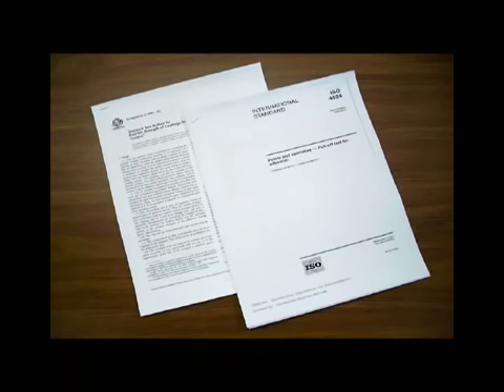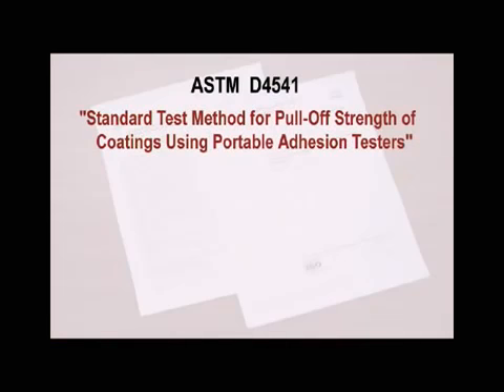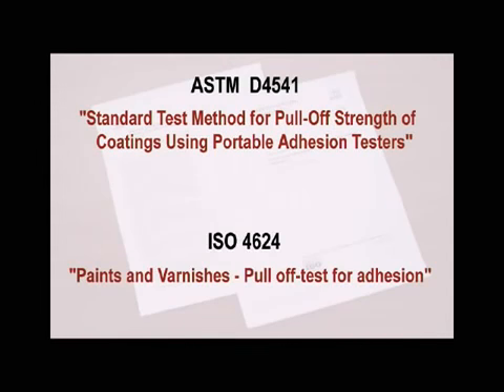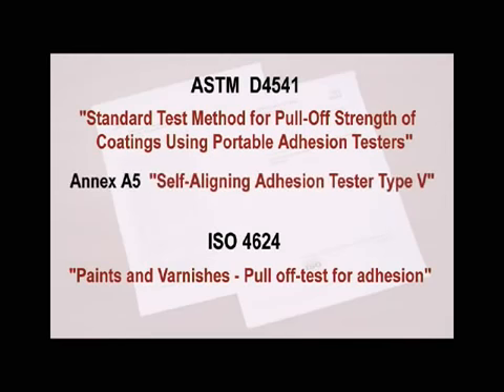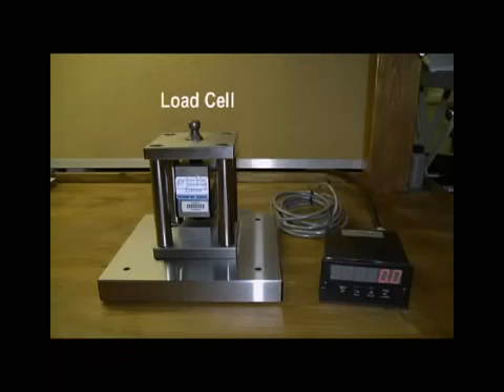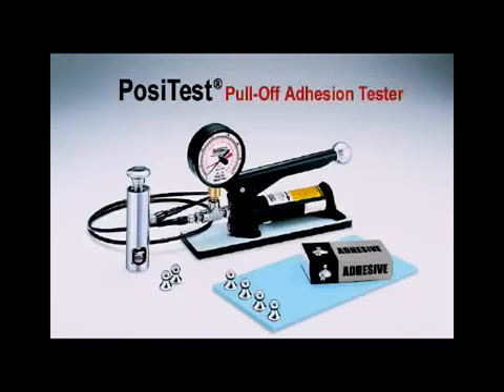The two most common standards for pull-off adhesion testing are ASTM D4541 and ISO 4624. The DeFelsko Positest pull-off adhesion tester shown throughout this video is specifically identified in Annex A5 of ASTM D4541. Every Positest adhesion tester pressure system is calibrated and certified to a plus or minus 1% full-scale accuracy using a NIST traceable load cell. Several Positest models are available for measuring coating adhesion on a variety of substrates.